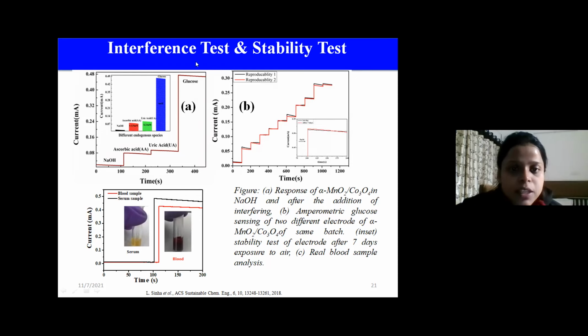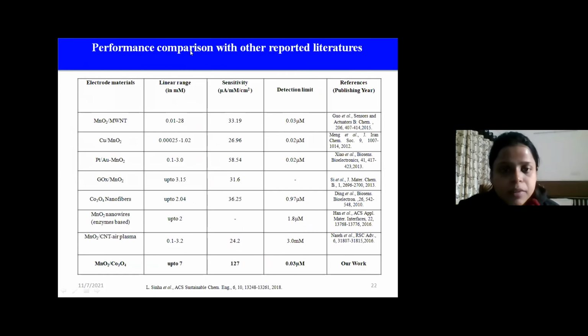So this is the interference test, and we are seeing that the material is giving higher sensitivity for glucose. Like in blood, other materials are also present, like ascorbic acid and uric acid. So the interference test has been done to see whether the material is suitable for glucose sensing or not. Here we can see that it's giving a higher sensitivity towards glucose. Now, compared with other reported literature, we can see that the material is giving higher sensitivity with a linearity of 7 millimolar, and the detection limit is also very low, that is 0.023 micromolar.